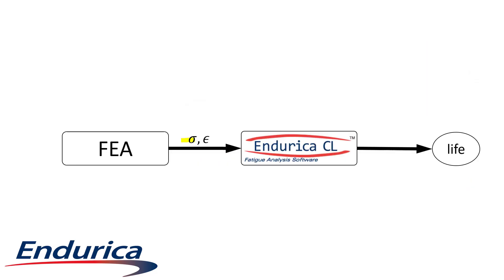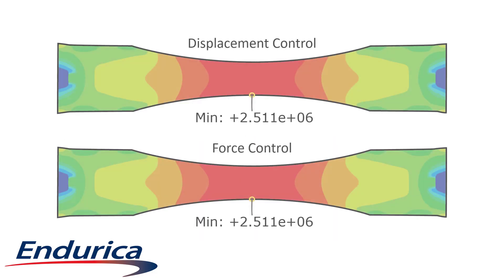If we solve the finite element models once for these two loadings and compute the fatigue lives without accounting for stiffness loss, we see that the two cases have identical fatigue lives. This is unsurprising since the displacement control and force control loadings are identical unless the models are updated based on stiffness loss.